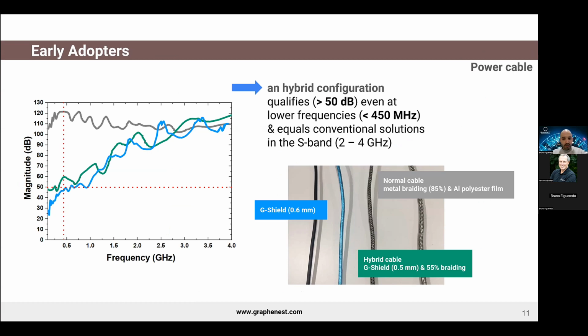Early adopters, such as power cable manufacturers, have seen remarkable results with our G-Shield solutions. After a long period of trials, it was possible to check that a hybrid configuration can be qualified for a power cable. So in this case, we decided to go with a hybrid cable which comprises 0.5 millimeters G-Shield and 55% braiding, which is the green plot.